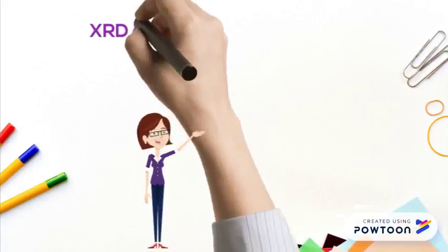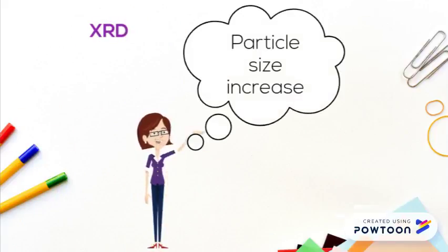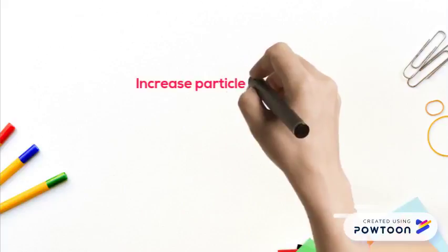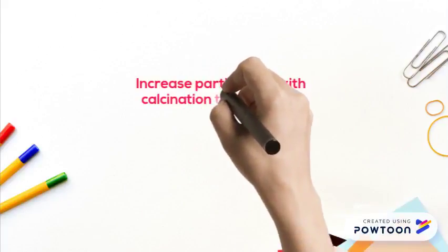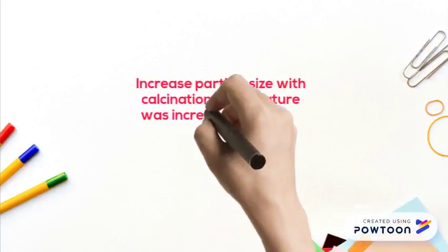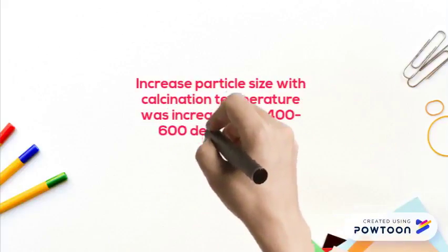For the XRD, we can see that the particle size increased dramatically when the phase transformed from anatase to rutile. For the morphology, we can conclude that the particle size increased with calcination temperature from 400 to 600 degrees Celsius.